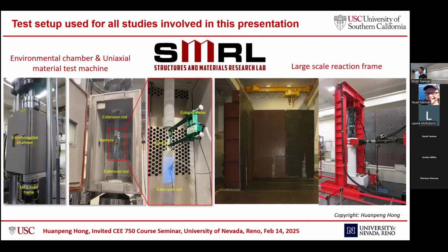So here I want to briefly introduce the test setup that is involved in all the experiments in this presentation. So later I won't repeat it again. For all the material tests on a material level, we use an environmental chamber and a uniaxial material test machine. When low temperature is involved, we use a liquid nitrogen tank to cool down the material. And when high temperature is involved, we just use electric current resistance to heat up the chamber. An extensometer is used to measure the deformation of the sample. And for the large-scale structural test, we use the large-scale reaction frame.